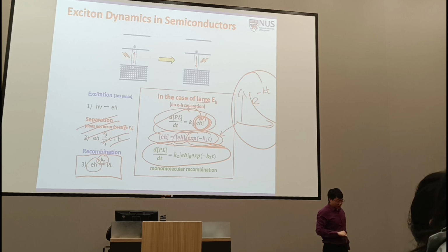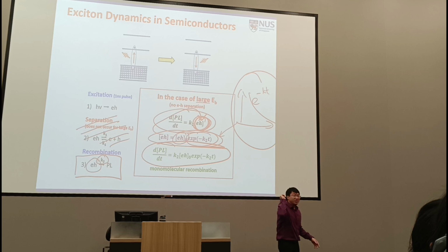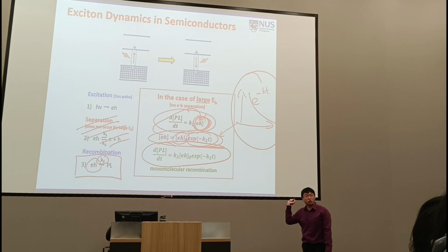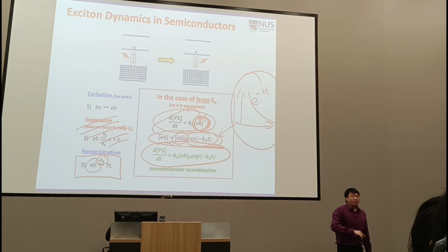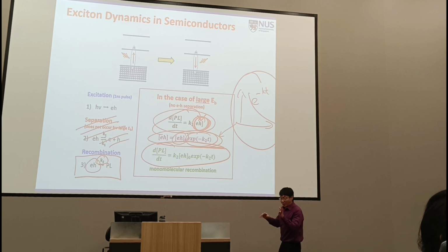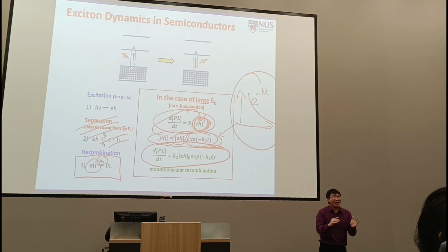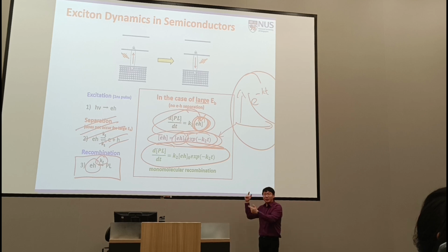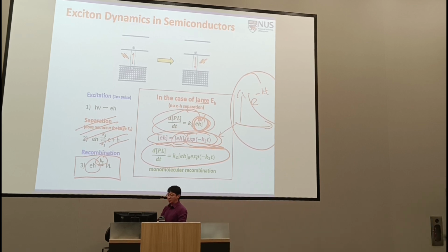And just for your information, in case you are thinking this happens in terms of seconds or minutes, no. This happens extremely quickly, in terms of nanoseconds. So you need a very sophisticated tool called TCSPC, which I actually have in my lab, but there are other labs that have it as well. It tracks photoluminescence over time, over very short times, nanoseconds or hundreds of nanoseconds. By looking at this, I can tell this semiconductor probably has a large exciton binding energy, right? So this is case one, large exciton binding.